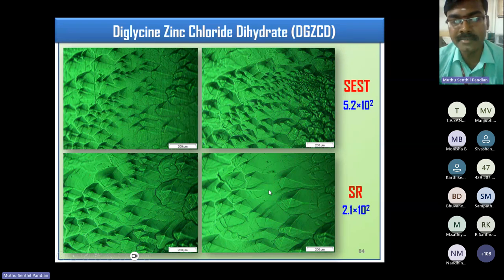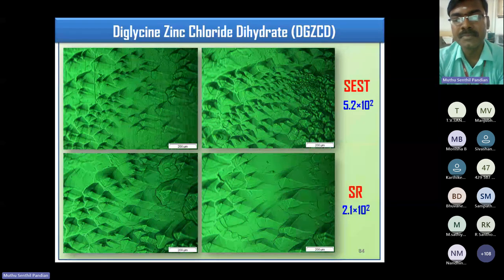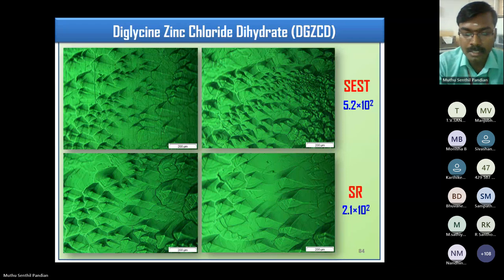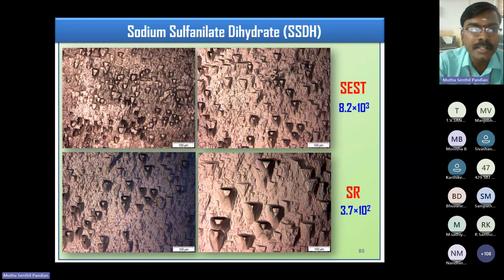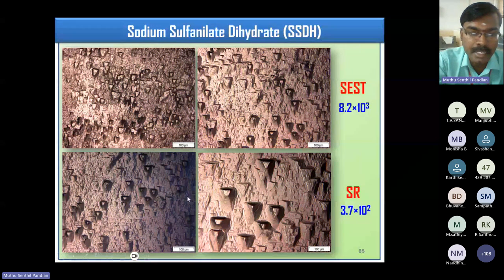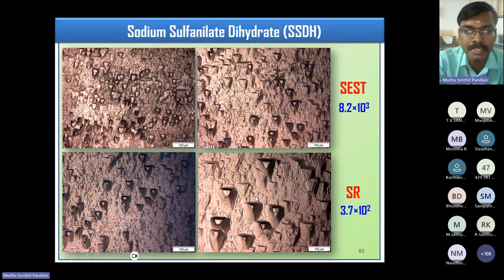Single and morphologically defined facets cause the very low etch pit density. And this is for the sodium sulfanilate dihydrate single crystal, and this is for the conventional method grown crystal, and this is for the SR method grown crystal. This is for 5 seconds, this is for 10 seconds. With successive etching for 5 to 10 seconds, the etch pits enlarge in size, retaining the geometrical shape, and do not disappear, suggesting that the pits are due to dislocations.